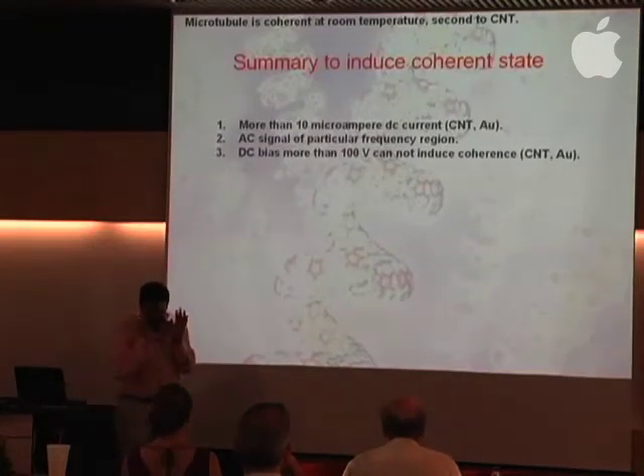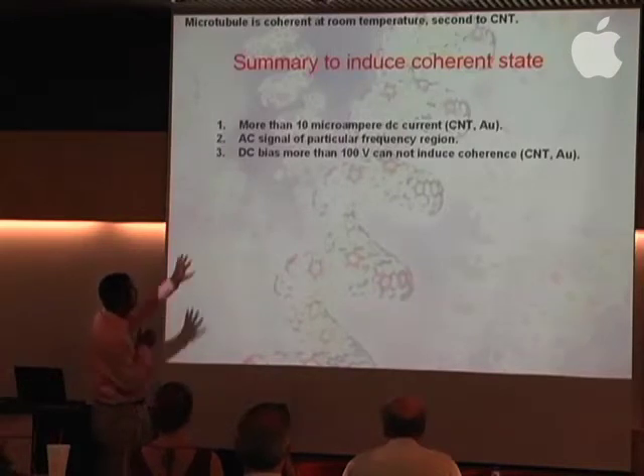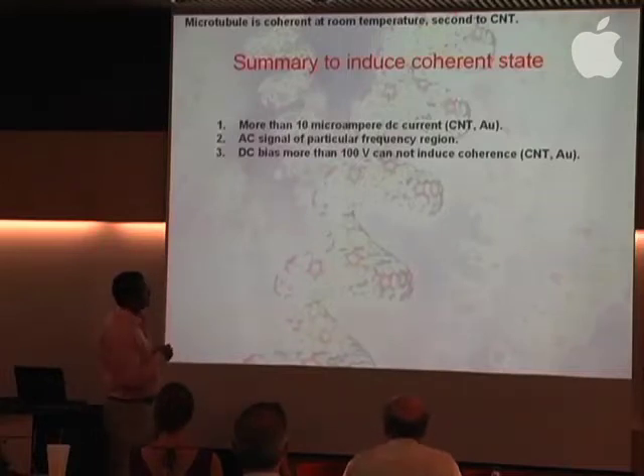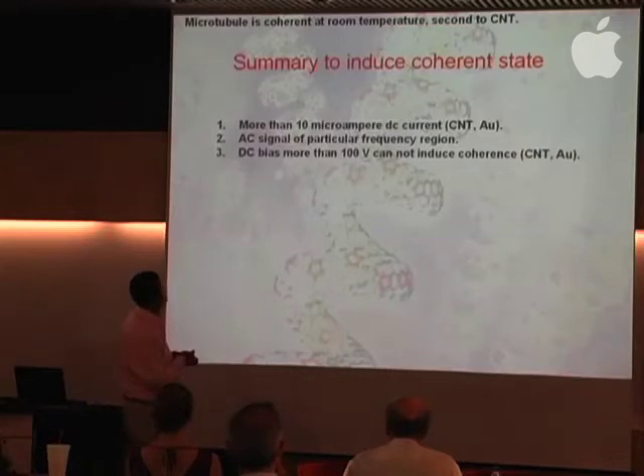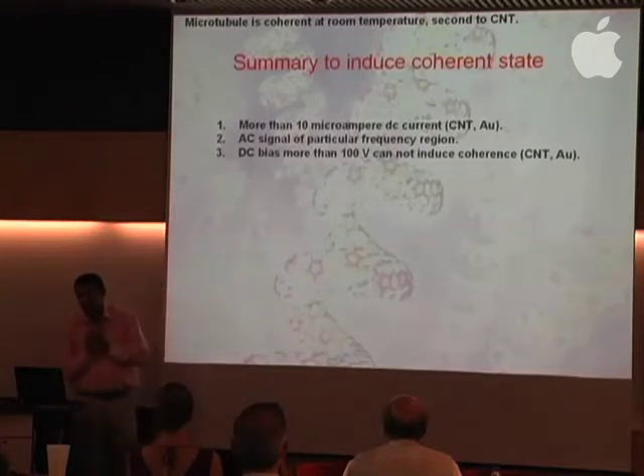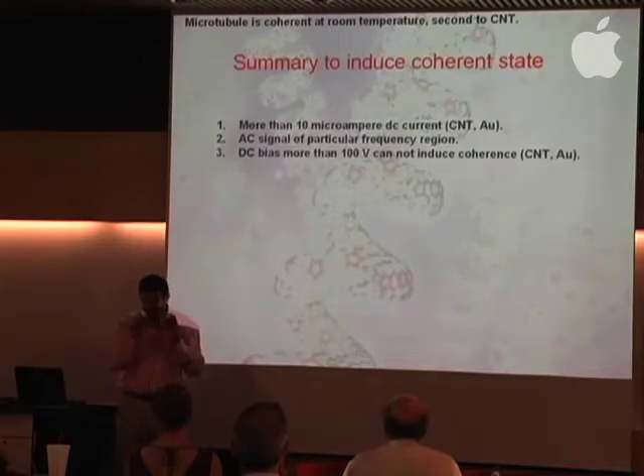So if we want to induce some quantum state, we found that around 10 microampere DC current is sufficient, and if you apply a large electric bias, you can't do anything. And an AC signal of a particular frequency region is sufficient. So we know what the recipes and protocols are to go to the quantum state.